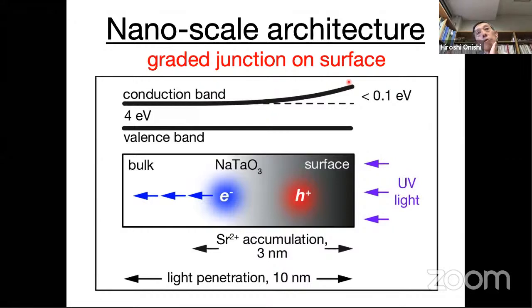And excited electrons should move in this way because the conduction band is lifted at the surface, not lifted in the bulk. So there is a slope. Electrons should go down along the slope. This means that the electrons move from the surface to the bulk of the photocatalyst particle. On the other hand, the hole should be present here, and does not need to migrate in this way. So the hole should remain here. Hole here, electrons there. So electrons and holes are separated in space.